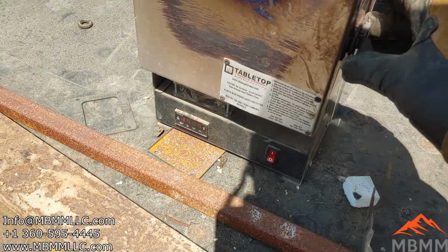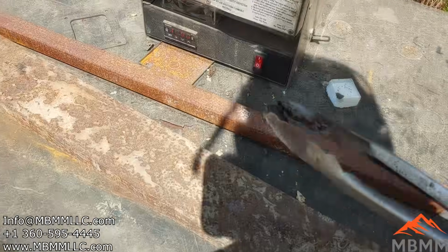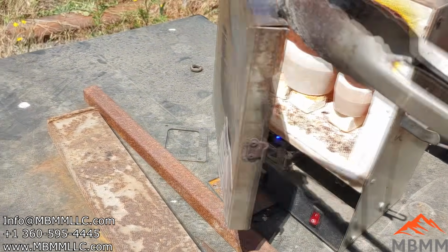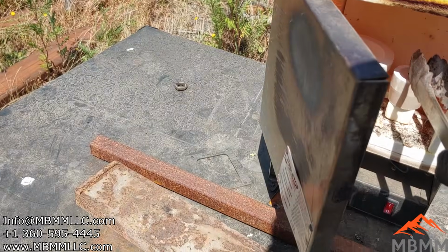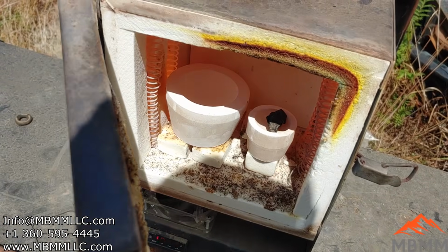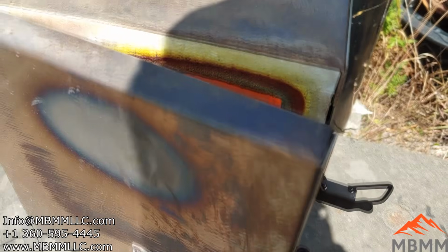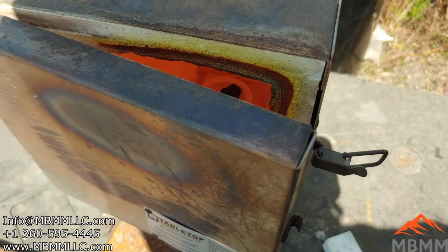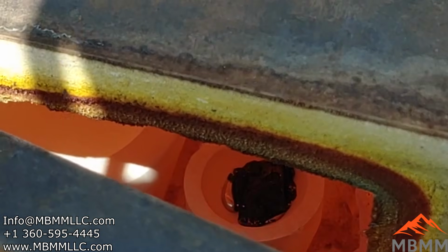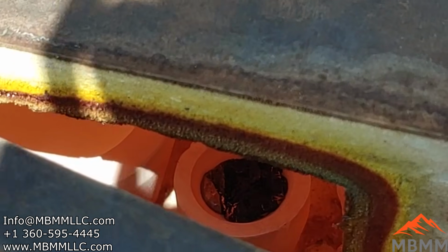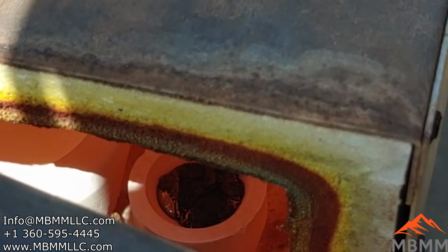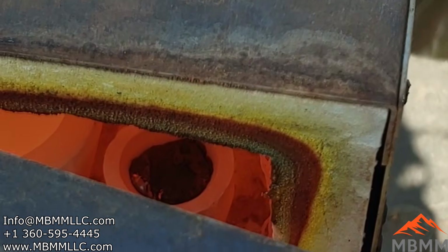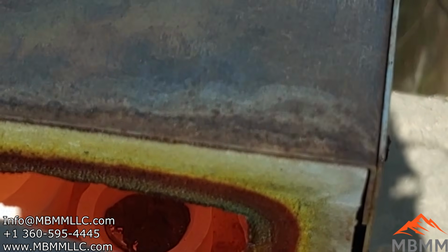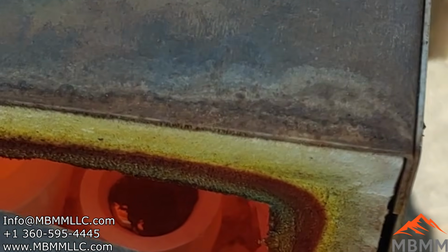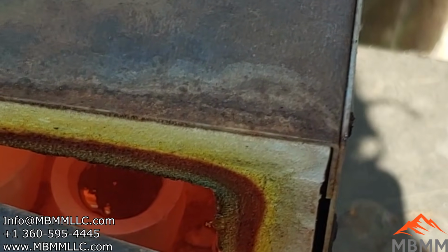Okay, here's our furnace. And our little lead block. Put in there, that'll start melting. There it goes. Now as that gets heated up and the surface oxidizes, that lead oxide will start being absorbed by that cupel, and the cupel will turn kind of a dark color, dark gray, dark brown. So we'll check back on that in a couple minutes.